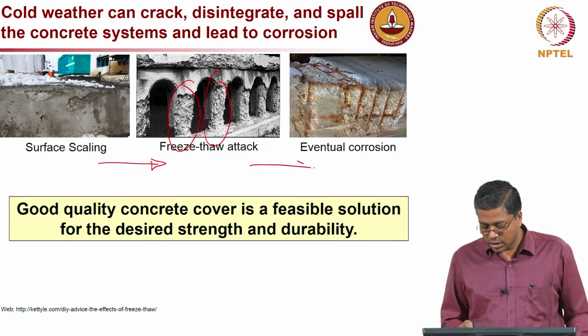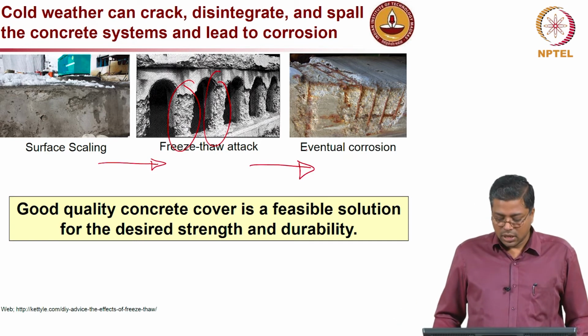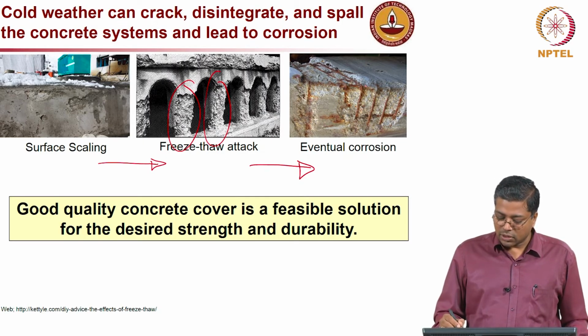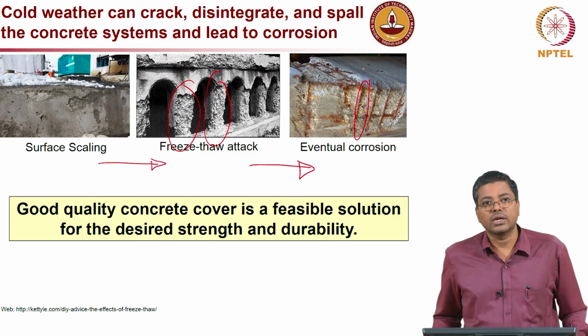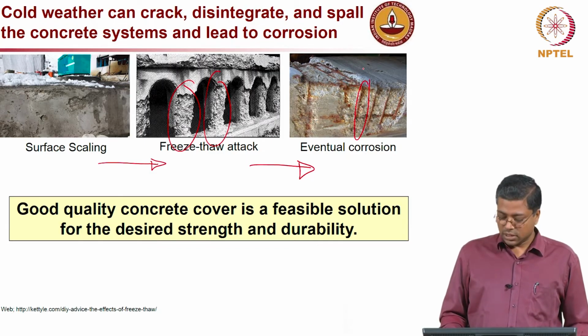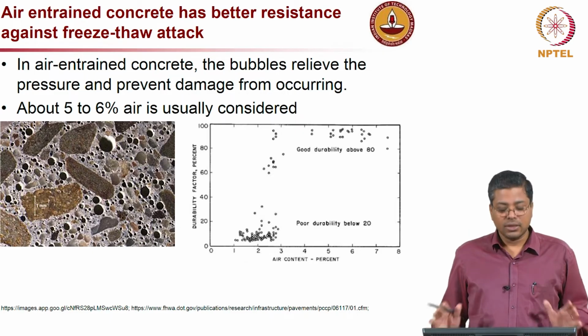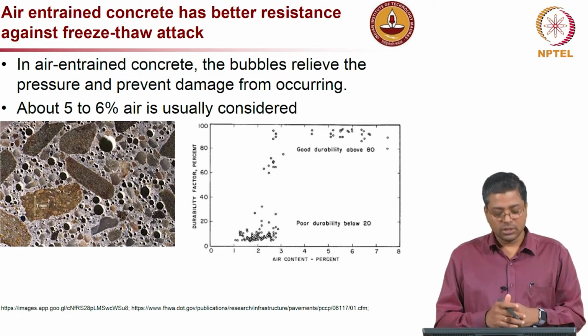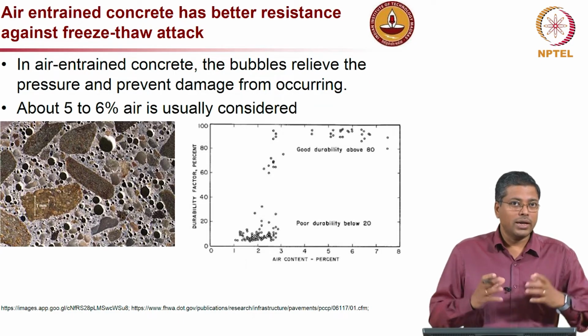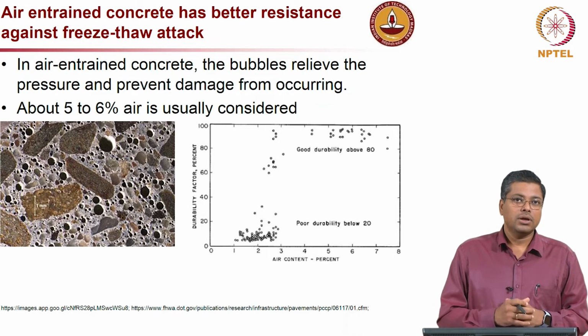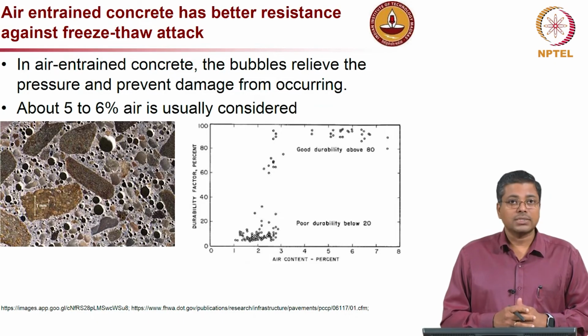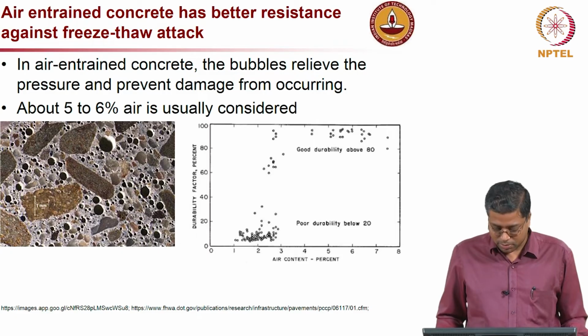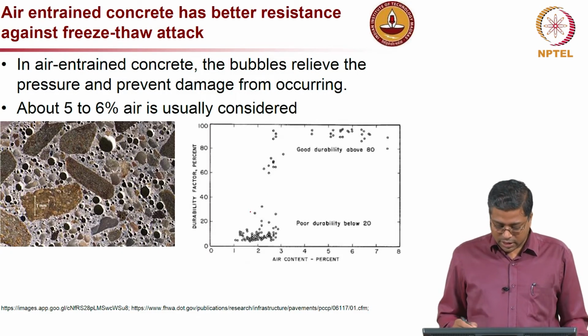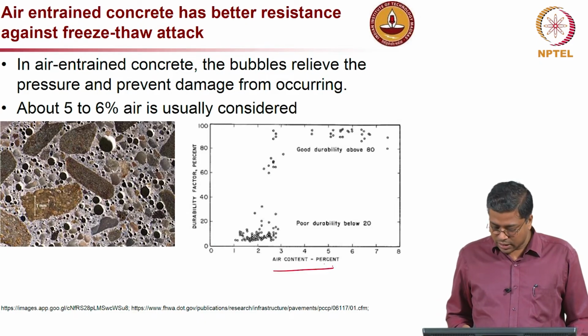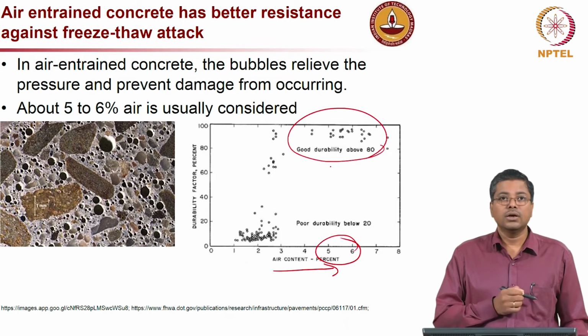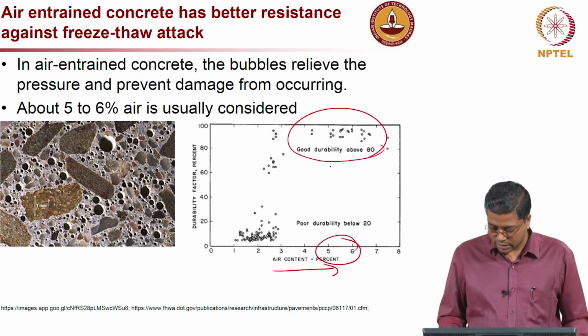Eventually the entire concrete cover can be lost due to this kind of freeze-thaw attack, and once the entire cover is lost, you will see the reinforcement getting exposed and corroded, which definitely affects the structural capacity of the system. So, how do we handle this? The main approach is to use air entraining admixture, so that you provide enough air void space in the concrete in which ice can form without exerting pressure onto the surrounding aggregates or the hardened cement paste. This picture also very clearly shows that if you increase the air content to about 5 to 6%, you have good quality concrete, or the durability factor is increased.